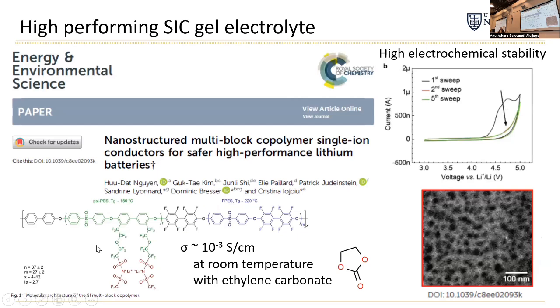And I would say, I think one of the leading papers in this area is this one, which I think is from like 2019, so maybe like 5 years ago. And they actually produced a material that's swelled with ethylene carbonate, which is used in commercial lithium-ion battery electrolytes. This molecule here can give you conductivities on the order of 10 to the minus 3 Siemens per centimeter at room temperature. And I just want to point out some of the features of this polymer.